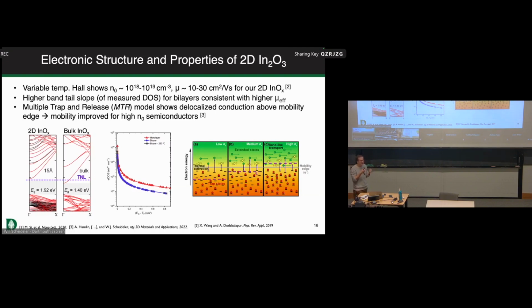But essentially, if you make materials that are higher in their electron concentration, like the two-dimensional oxides that we're developing here, there's this inherent benefit to being able to avoid the localized transport in these mid-gap trap states and get delocalized transport that looks a lot more like a single crystal semiconductor.